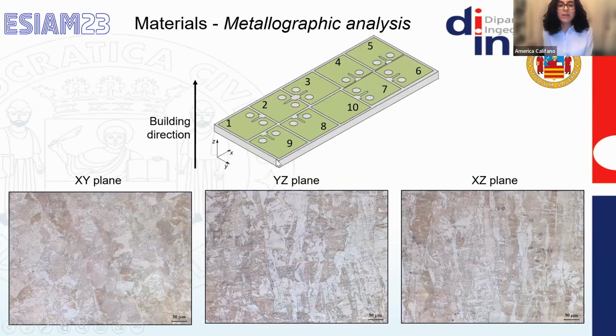So concerning the metallographic analysis that was carried out on one of the specimens, if we bear in mind that the building direction was direction Z, as shown here in the slide, and if we take a look at the macrographs, it is quite clear that the YZ and the XZ planes, so the planes that are along the building direction, are characterized by very thin and slender grains that are easily visible from the macrographs. So they share similar behavior, while the XY plane that is orthogonal to the building direction has a more homogeneous macrostructure.